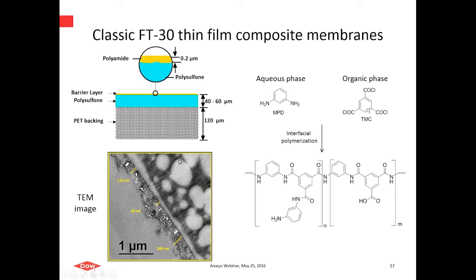The polyamide layer is made by interfacial polymerization, and that's a reaction of an aqueous phase containing metaphenylenediamine with an organic phase that consists of trimesoyl chloride. It's reacted to form this amide linkage at the interface with pendant amine and carboxylic acid groups.